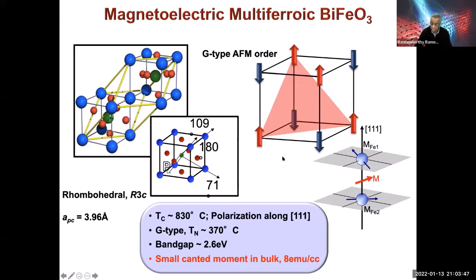And there is also something more sophisticated, called the Dzyaloshinskii-Moriya, or the antisymmetric spin coupling, S1 cross S2 kind of a term. That leads to a canting of the moment. And this canted moment actually is very important for coupling to another ferromagnet. It's only a small value of about 8 emu per cc.